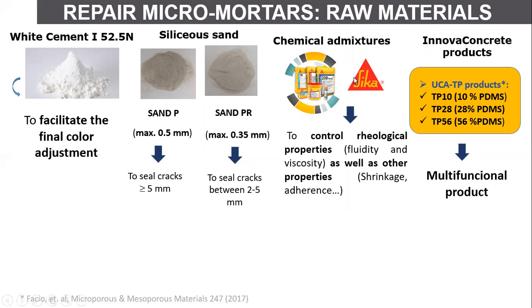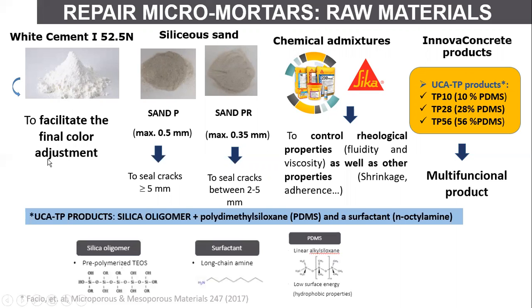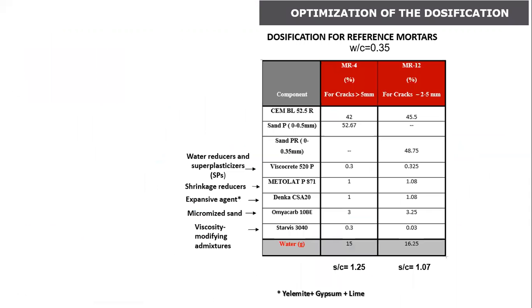And finally, we have incorporated the UCA-TP products, which are multifunctional products based on a mixture of a silica oligomer, a surfactant, and a polydimethyl siloxane. This last one has been added to provide the hydrophobic performance. The polydimethyl siloxane has been incorporated in 3 different proportions, 10, 28, and 56% by weight. Well, with the previous raw materials, different dosifications were tested until we obtained 2 reference mortars.